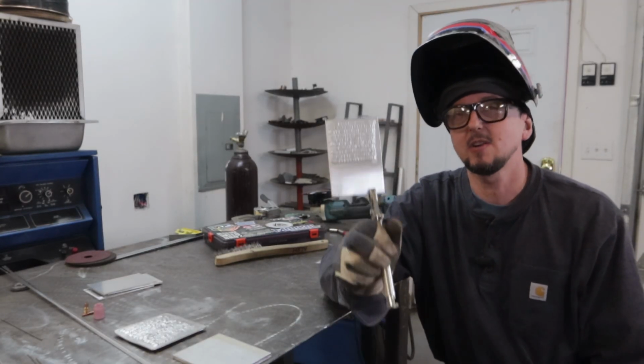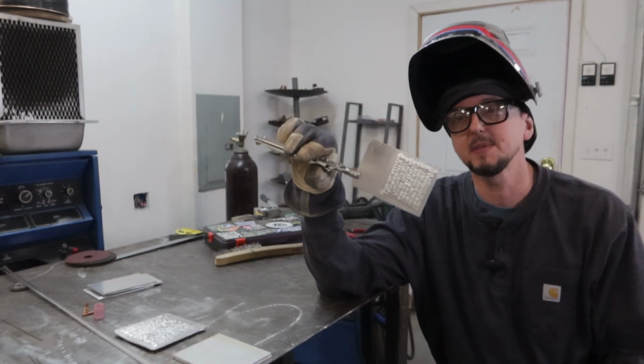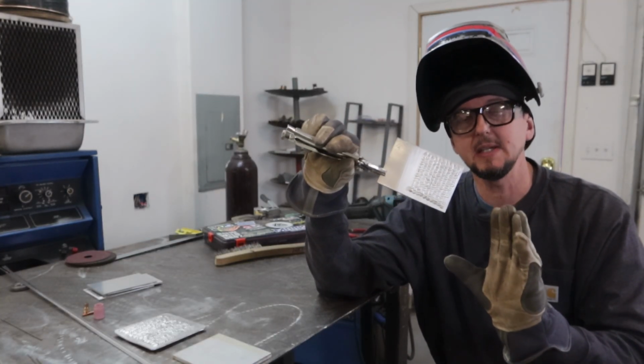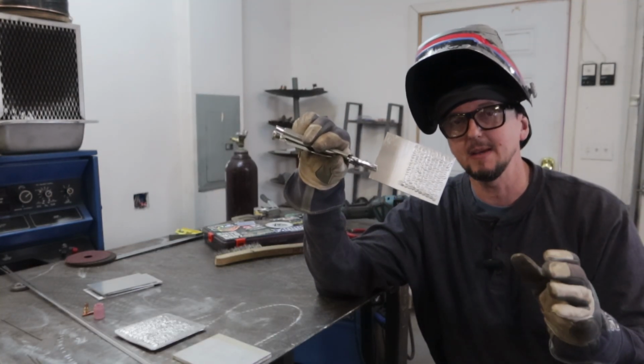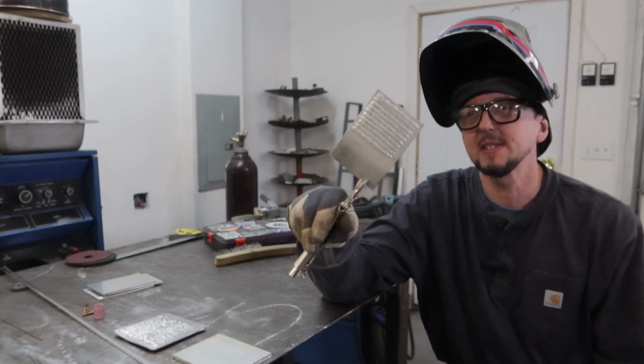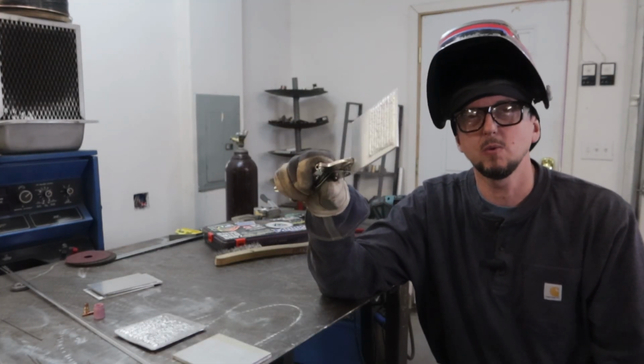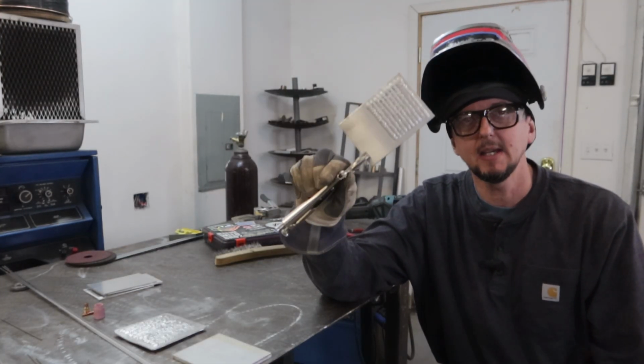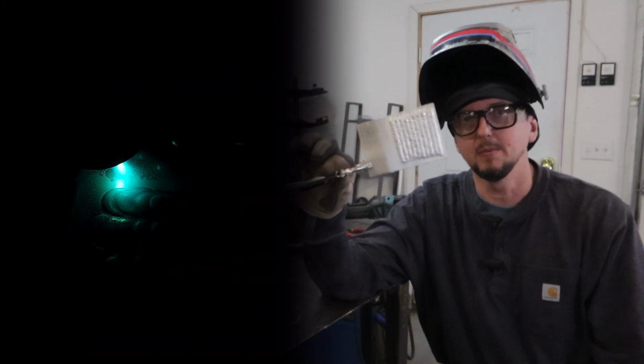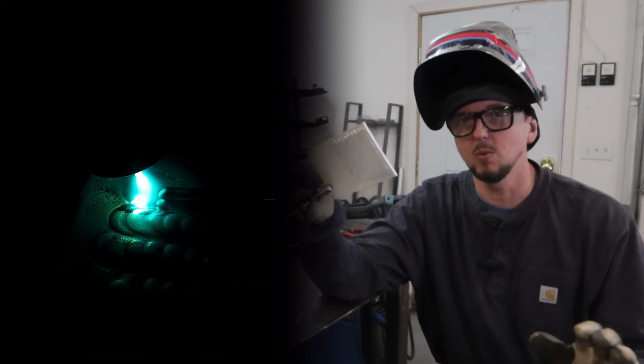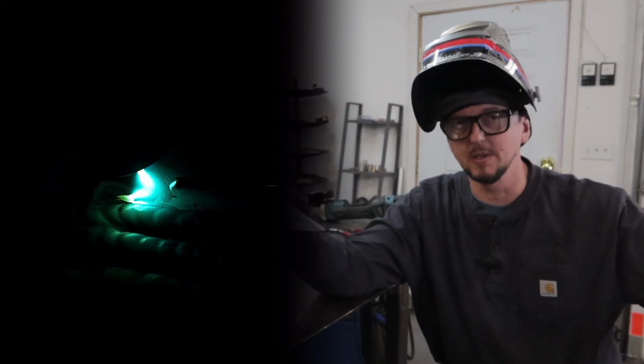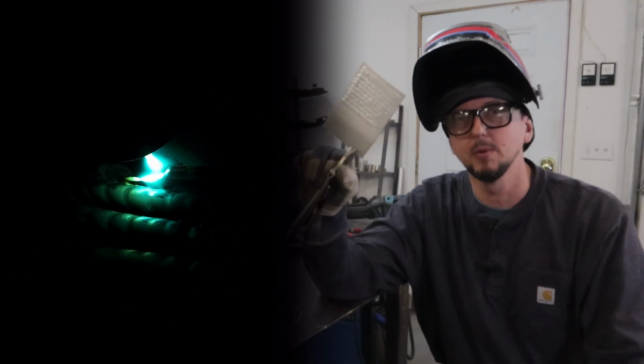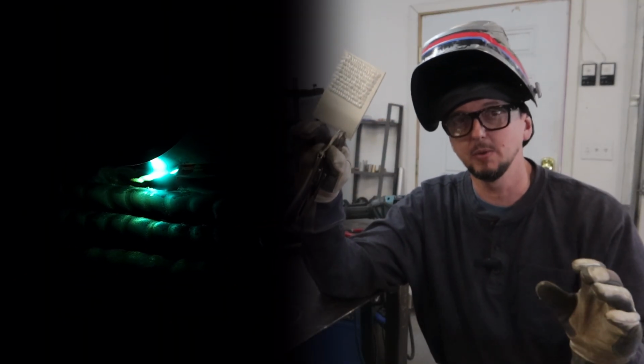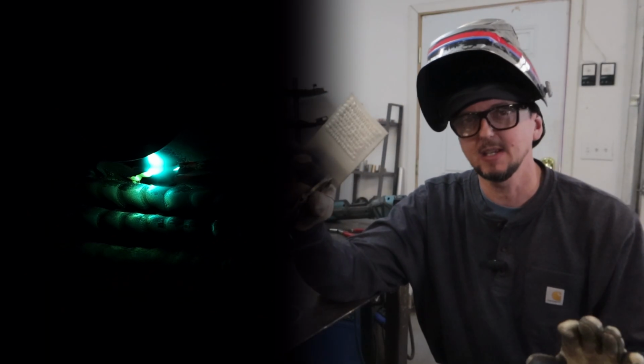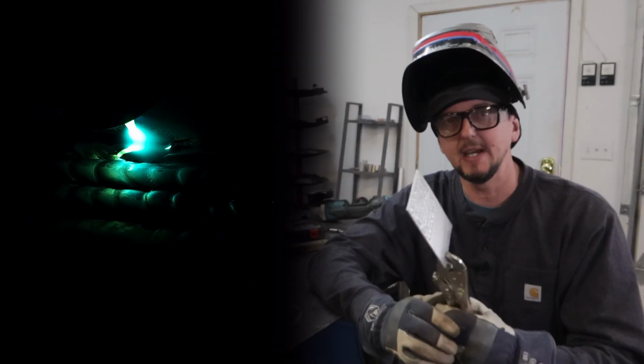Another thing is, I started out at 140 amps for my very first bead, but then I'm turning it down 5 amps at a time. The lowest that I go is probably 125 or 120. And then, when it gets to the point where at 120, it's really, really hot and the weld pool is really, really fluid immediately, then I'm just going to stop. You just got to let it cool down.